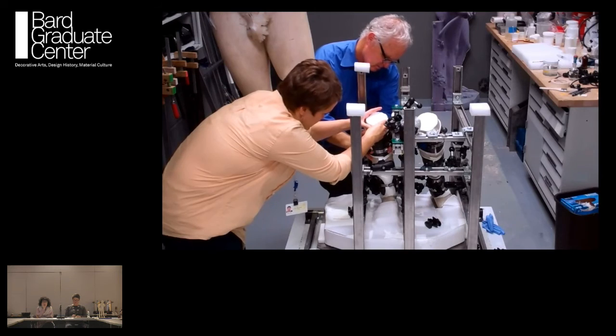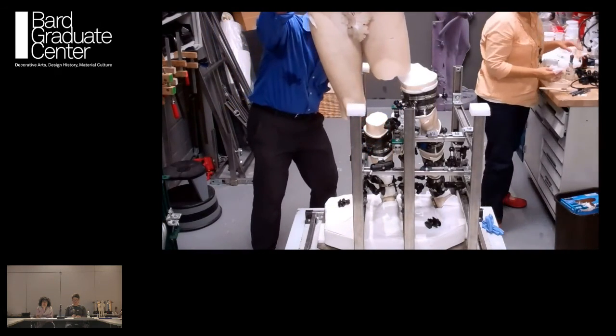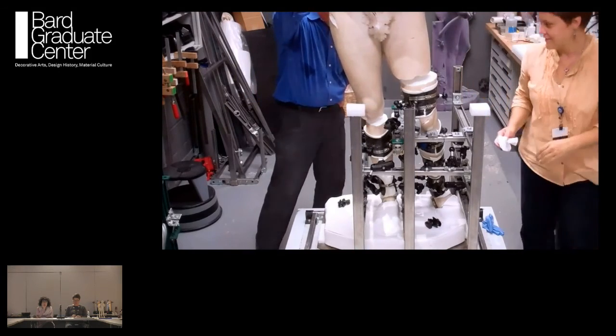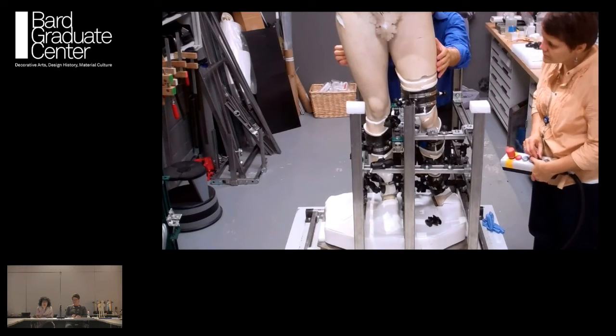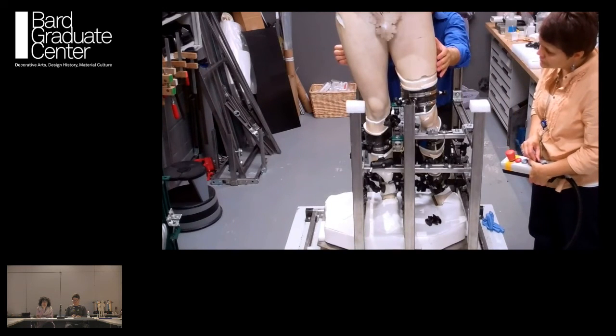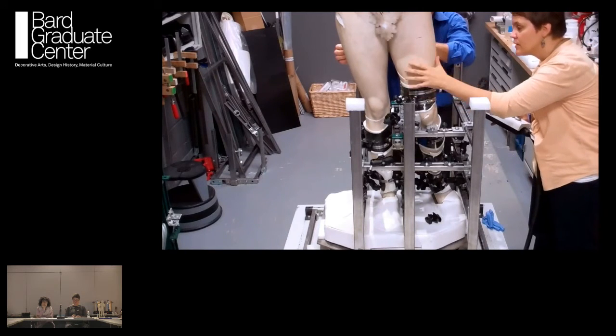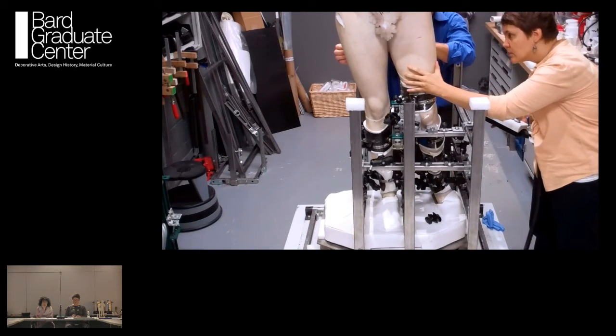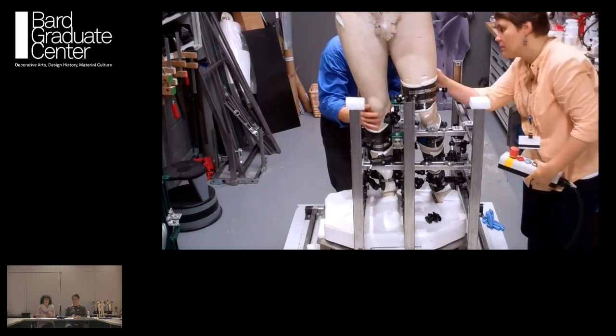The dry stacking method also allowed us to monitor the alignment of the fragments with each joint that was bonded. Once the fragments were fully assembled, the sculpture was left alone, immobile for at least 1 month, because acrylic adhesive set by a process of solvent evaporation. Only then were the legs disassembled, and the process was repeated again for a different joint.